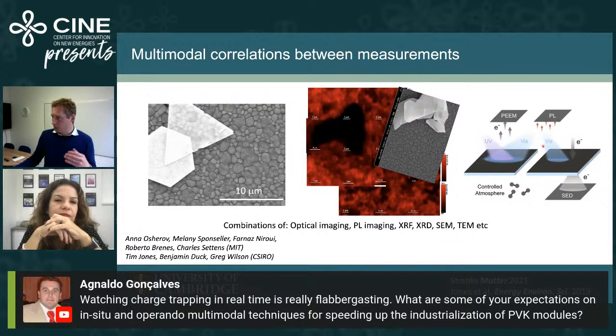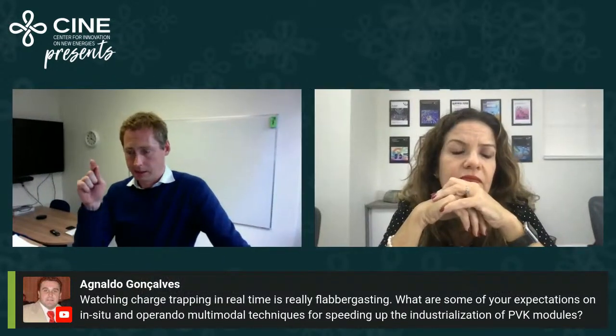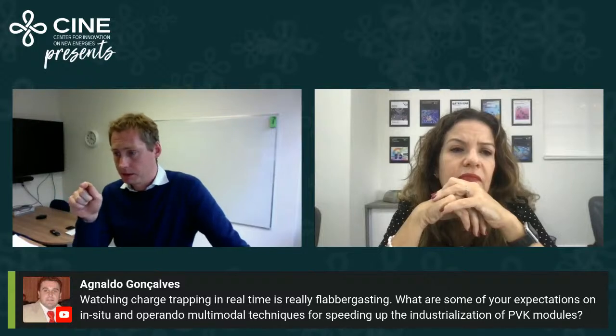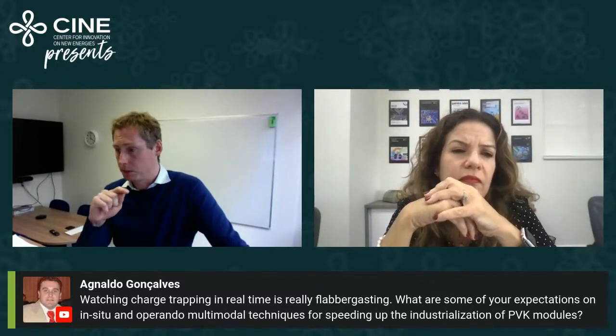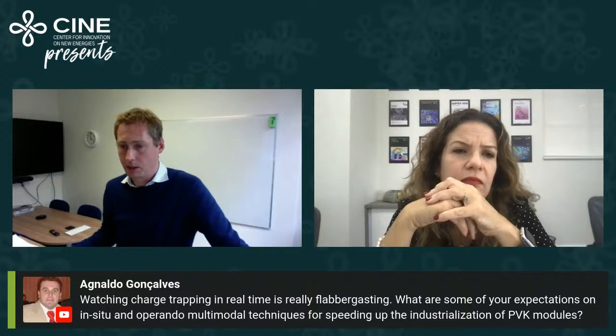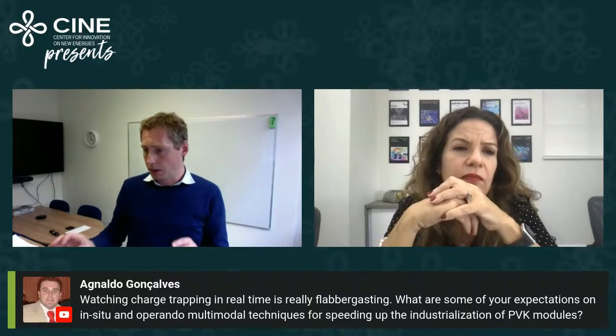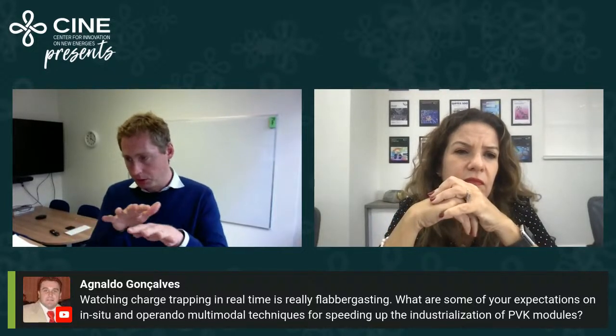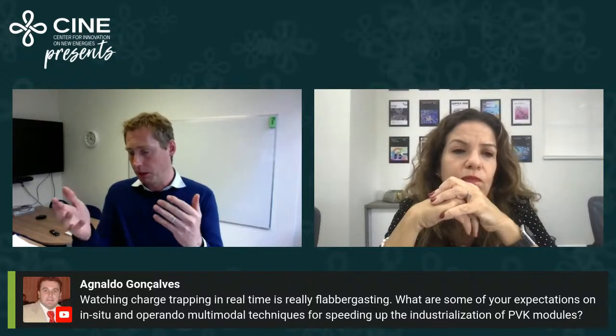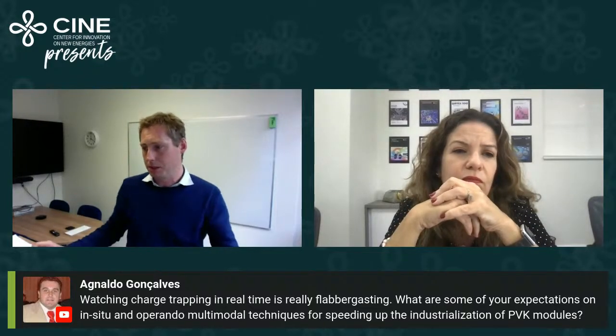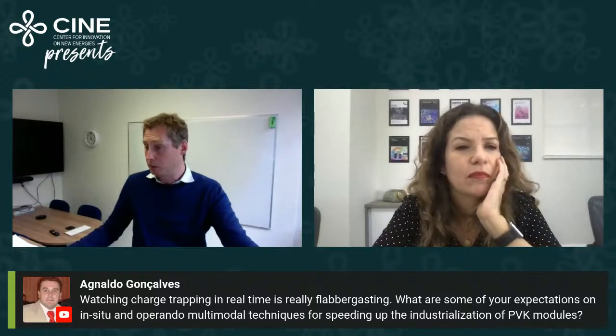The electron microscopy is difficult to make high throughput, for example. So if you think about a roll-to-roll line, that's going to be difficult to ever really have something online. But what we're starting to understand is the connections between them and other properties, like photoluminescence. So with a particular photoluminescence type feature, we may be able to know what sort of structure it is, even though we may have lower resolution with the PL. So we're able to draw relationships between the quantities, and therefore we can use quantities that are accessible to screen them, for example.